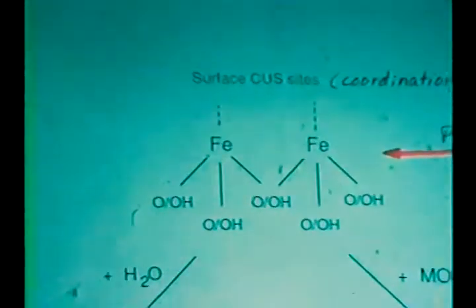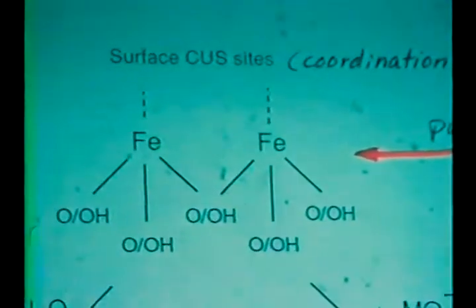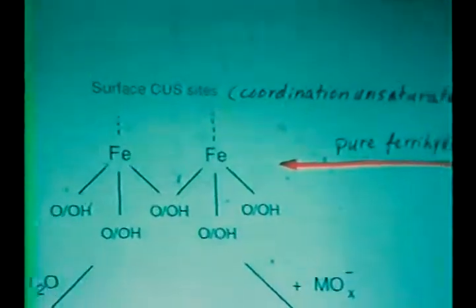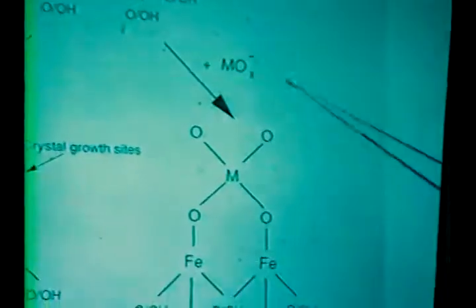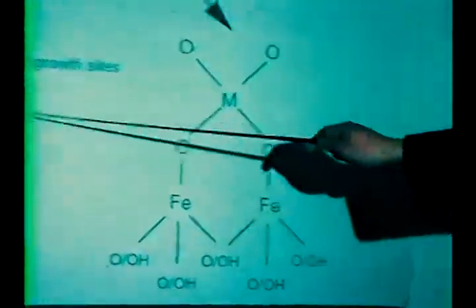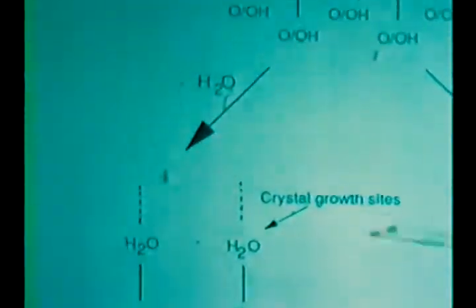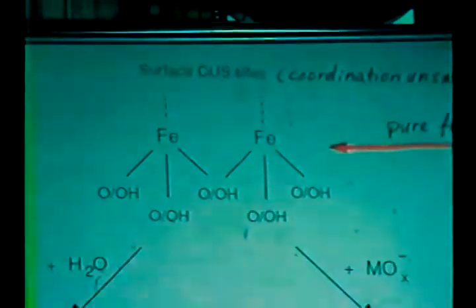Let's look at the model again. This is the structural model for ferrihydrite. With water, maybe we can say these sites become the crystal growth site. On the other hand, if we put some impurity ions in the solution, probably this site will adsorb the impurity ions instead of water, and then we can block the crystal growth site.